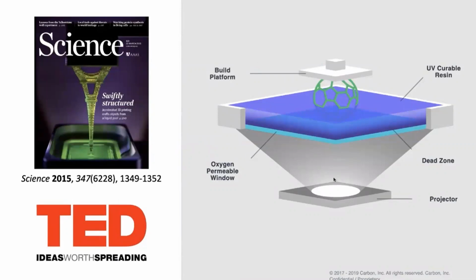And the key technology is a DLP-based approach where we're using light at 385 nanometers, illuminating a reservoir from underneath using the light. At the bottom of this reservoir of liquid, there's a very special window. And the window is not only optically transparent, but it's also highly permeable to oxygen.